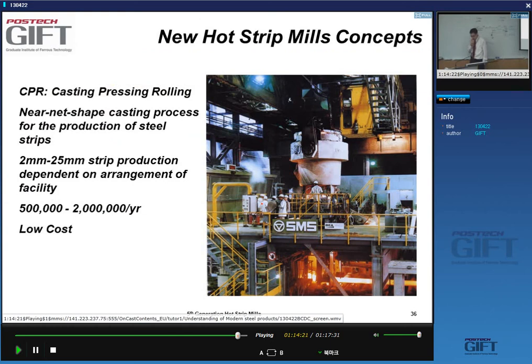Right, so these are basically the most important technologies that you should remember as alternative to hot strip mill: the CSP technology and the ISP, or in the case of POSTECH, the CEM technologies. There are other technologies, in particular interesting is the CPR, casting, pressing, rolling. And here the idea is basically to have a hot strip production that uses a near net shape casting. So you're basically trying to cast the product and to make very thin, 2 millimeters to 25 millimeter strip production, without much rolling at all.